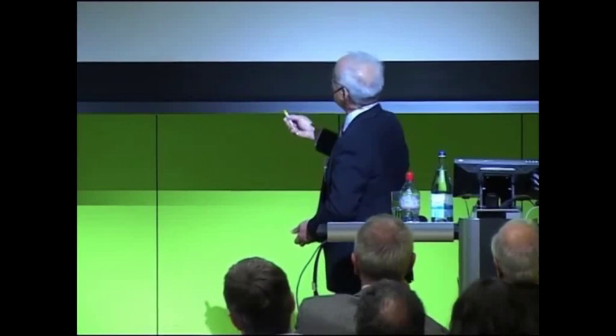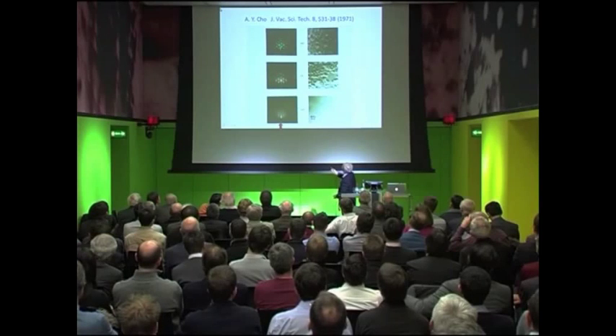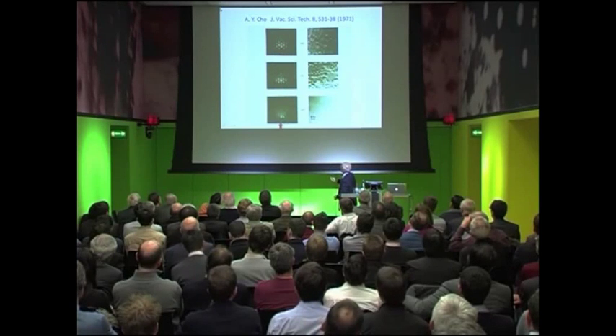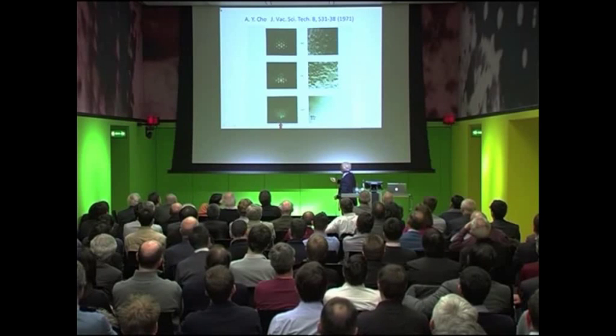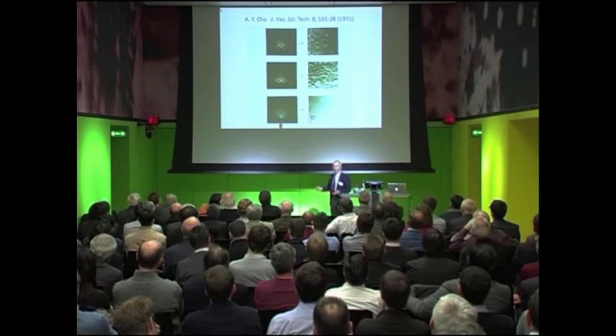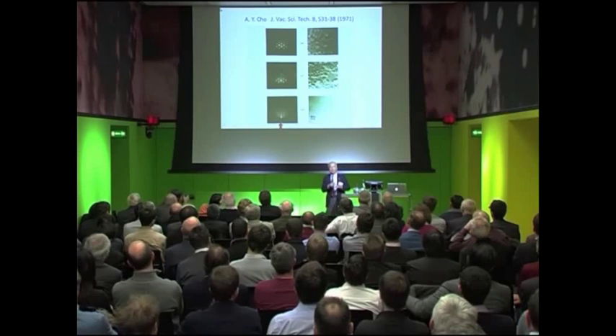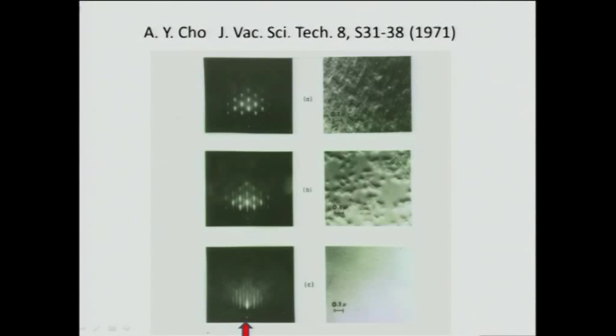Furthermore, I want to show you here, notice after the diffraction gets smoother and becomes rods, we see a 1/2 order diffraction showing up. What is the 1/2 order about? It's because the MBE further can see the surface atoms, the reconstruction of the surface atoms. They are 2 times larger, in this particular case in the 110 direction, than the bulk. In reciprocal space, 2 times larger is 1/2 order. So we have 1/2 order diffraction.